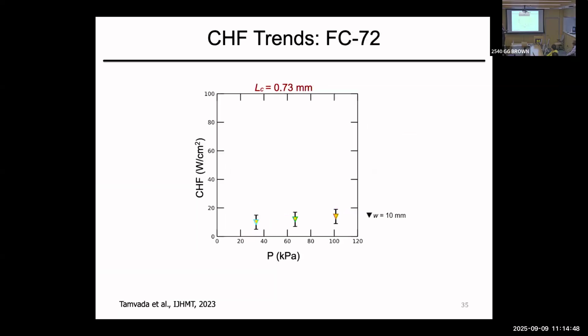So let's look at FC72. If you go again for a 10 by 10 millimeter, a large surface, you get results consistent with Zuber. As you go to 2, 1, half, you keep increasing. Experimentally, for us, it's not possible to go below 0.5. If you did, I do believe that we would have capped out with FC72, but there is no observation of that.